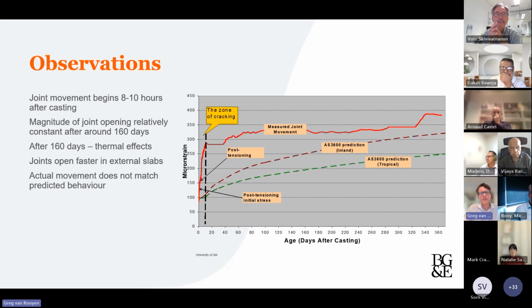When we have a look at the results, the red line. So I suppose it's important to start looking at these dotted lines here, which are the prediction from the standard, AS 3600, and we can notice straight away that a lot of the joint opening and the movement occurs 8 to 10 hours after placement. And then after about 160 days, it's fairly constant. You're really just measuring thermal effects. There's more joints opening up more quickly in external slabs, but a key thing is that this behavior doesn't match the predicted behavior.